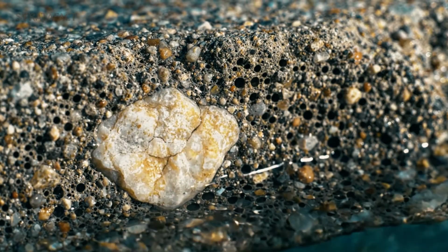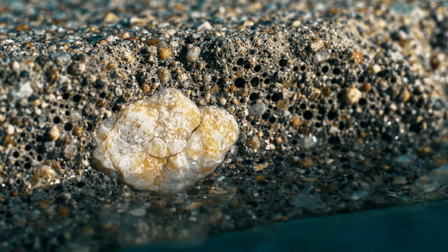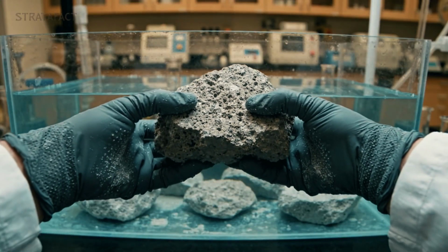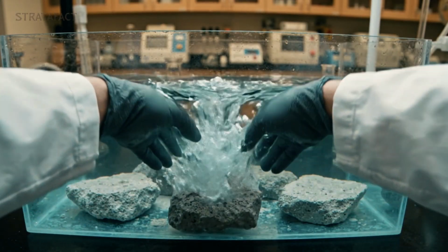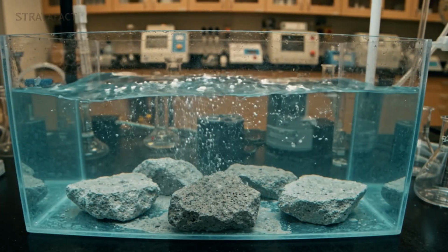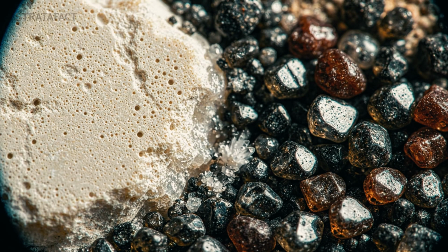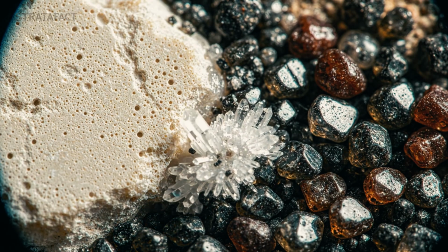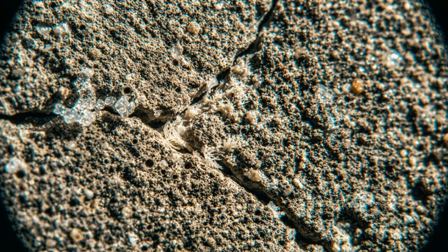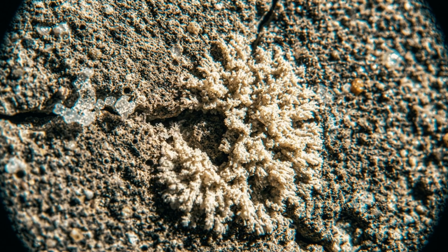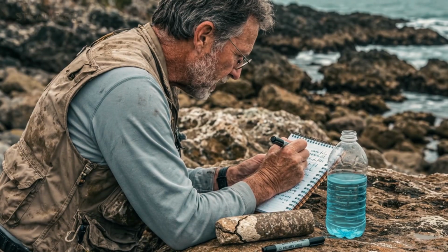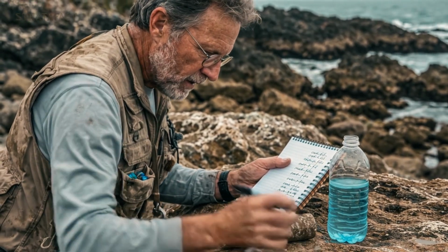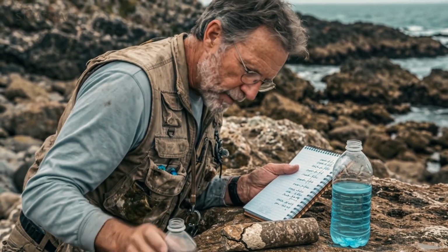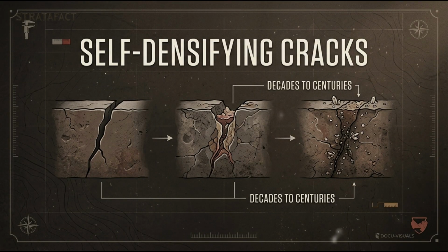Seawater percolates through the microscopic pore structure of Roman marine concrete over time. When it reaches areas where the lime has not fully reacted with the pozzolana, areas that remain chemically reactive even after the initial set, the calcium in the seawater combines with the aluminosilicate glasses in the pozzolana to nucleate tobermorite crystals. These crystals grow slowly, over decades or centuries, filling the microcracks and pore spaces in the concrete. The material, rather than degrading as seawater penetrates it, incorporates the seawater's mineral content into its own structure and becomes denser and stronger in the precise locations where degradation was beginning.